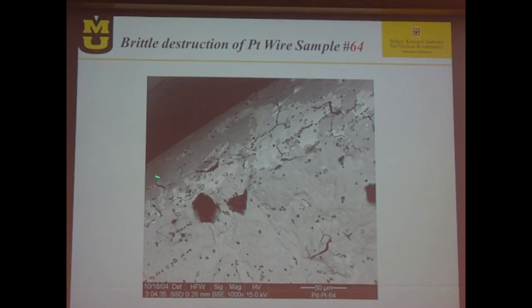And look what defects due to the temperature. And actually, if you look closely with SEM, you will see spots of palladium. So there was migration of palladium from the cathode to the platinum wire, close to the cathode. So a tremendous amount of heat was released.